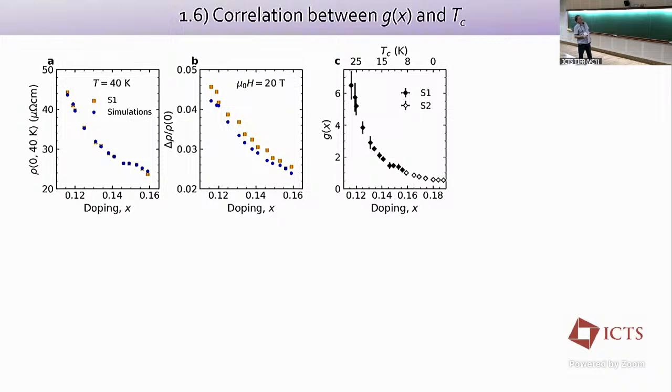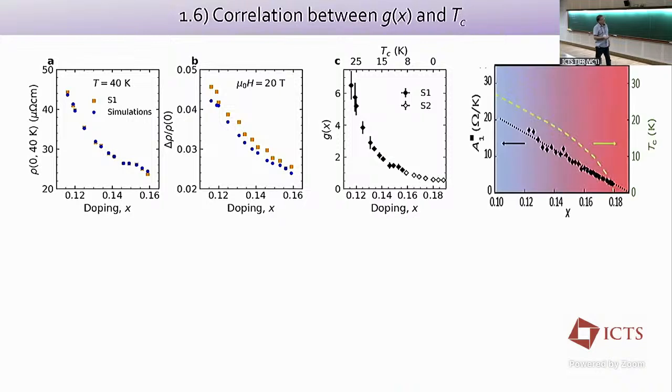We fit the size of the magnetoresistance. I showed how it was dropping away as you go down. And so the extracted value for this coupling parameter is going down quite strongly, by roughly an order of magnitude across the whole series. And of course, we know that the parameter for the A coefficient also varies by almost an order of magnitude over the same regime.